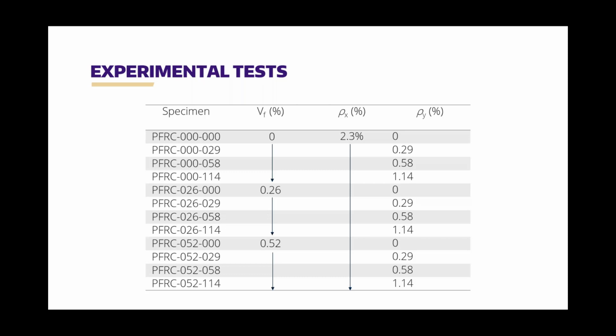So the test series, we ended up testing 12 panels in all. They had 3 volume fractions of fibers, so panels without any fibers, then panels with 0.26% and 0.52%. And those percentages seem a little odd, but it's really 4 pounds per cubic yard and 8 pounds per cubic yard. And 8 pounds per cubic yard is actually the maximum addition rate that the fiber manufacturer recommends. And in the longitudinal direction, all the panels had 2.3% steel, and in the transverse direction, we then had 4 different levels again. So we had, of course, no transverse reinforcement up to the maximum transverse reinforcement that would be allowed for this specimen size.